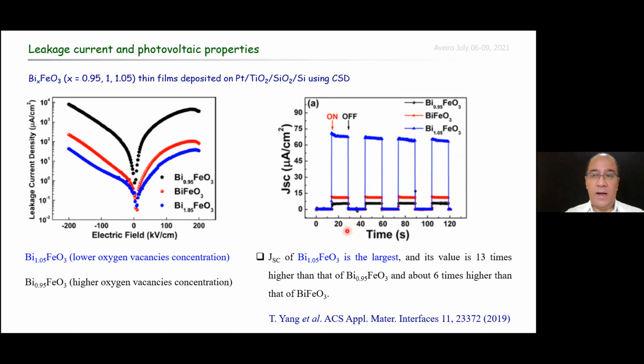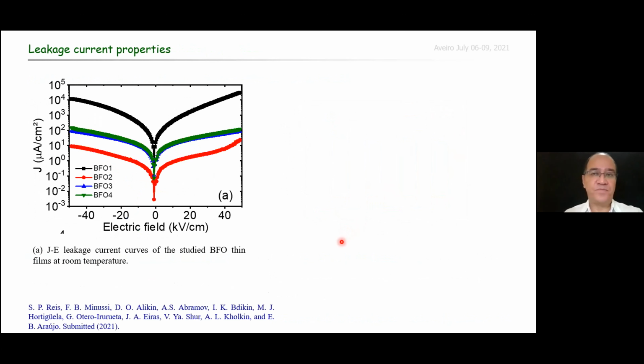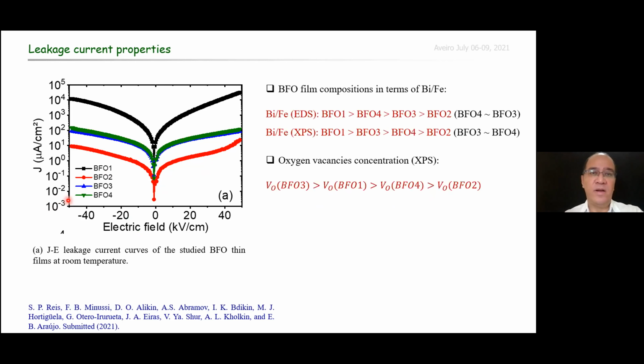We performed a similar study in our BFO films. This figure summarizes the leakage current of our studied BFO thin films. As shown before, from EDS and XPS quantifications, the bismuth iron ratio is higher for the BFO1 film, lower for bismuth deficient BFO2, and intermediate for BFO3 and 4. For these two last samples, 3 and 4, the bismuth iron ratios were almost the same within the instrumental error.